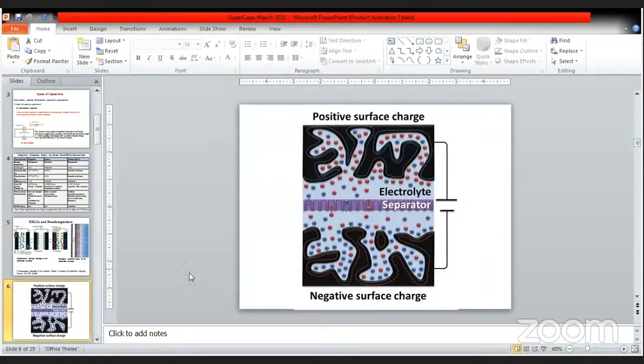And if you see the broad picture of charge storage, particularly for the EDLCs, the electrical double layer capacitors, the negative and positive charges go inside the pores, and porous carbon is utilized to form the active electrode material for supercapacitor application. And this is a physical barrier, a separator between the two electrodes, which separates the electron-conducting electrode material from the ion-conducting electrolyte. Okay. So this is a broader picture.